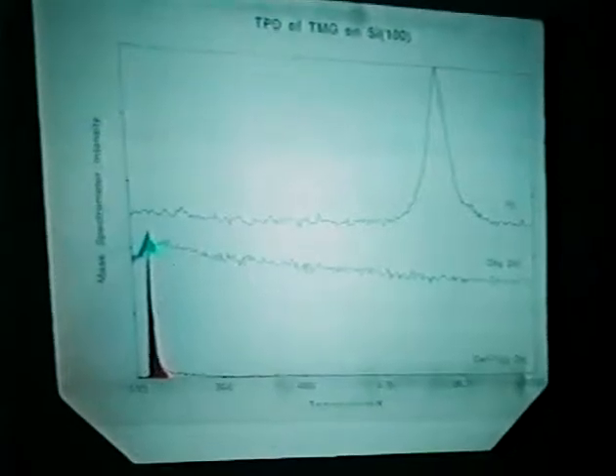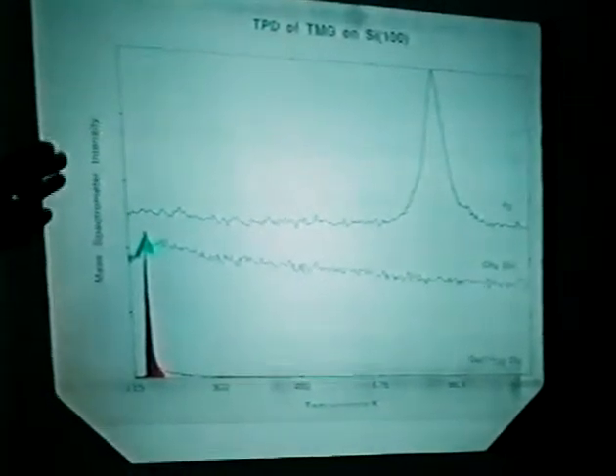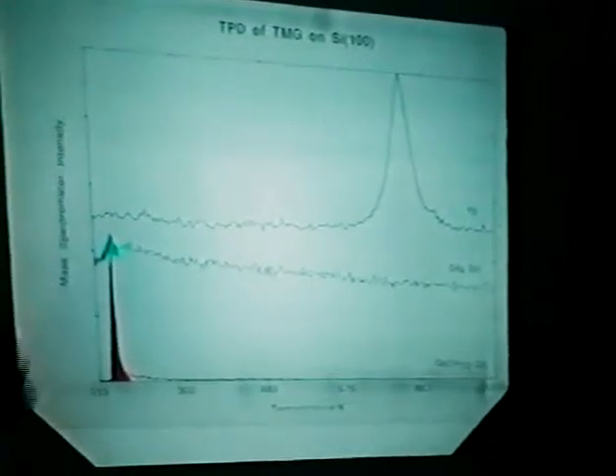Here's the temperature programmed desorption that summarizes what we see. We see the parent molecule at low temperatures. We see hydrogen at high temperatures. And under our conditions, essentially everything that adsorbs decomposes.